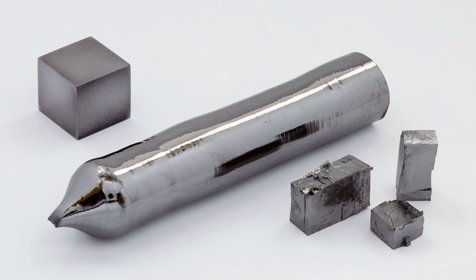Subsequent to removal of the niobium, the solution of purified H2TaF7 is neutralized with aqueous ammonia to precipitate hydrated tantalum oxide as a solid, which can be calcined to tantalum pentoxide, Ta2O5. Instead of hydrolysis, the H2TaF7 can be treated with potassium fluoride to produce potassium heptafluorotantalate. H2TaF7 + 2 KF → K2TaF7 + 2 HF. Unlike H2TaF7, the potassium salt is readily crystallized and handled as a solid.